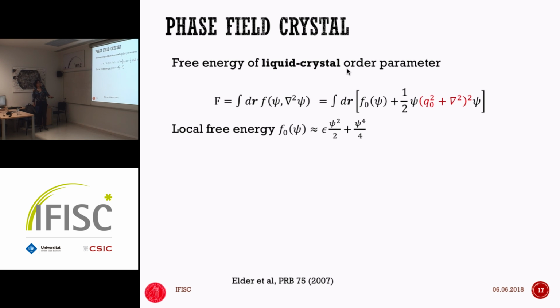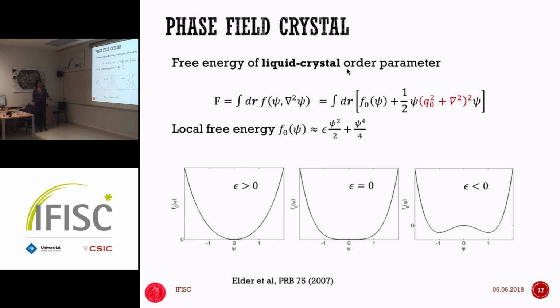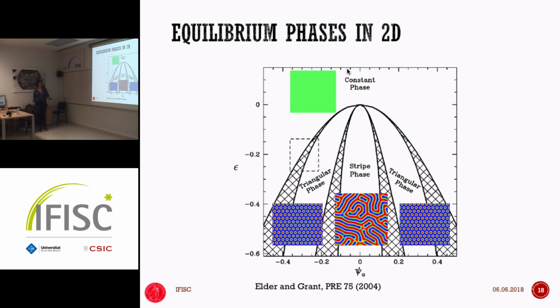And then the local term has different variants. I can just keep the logarithm, or I can also expand the logarithm around the equilibrium state, and I get the double well potential. So I know that I have a phase transition from a state that is uniform to potentially a state that has different symmetries. Okay, so if I calculate the phase diagram for this particular free energy, actually we see that it has a constant phase related to the equilibrium liquid, so there's no structure. And then depending on the quenching depth and the mean density, we can either have a crystal phase or a laminar phase. And there are also coexistence boundaries between them.